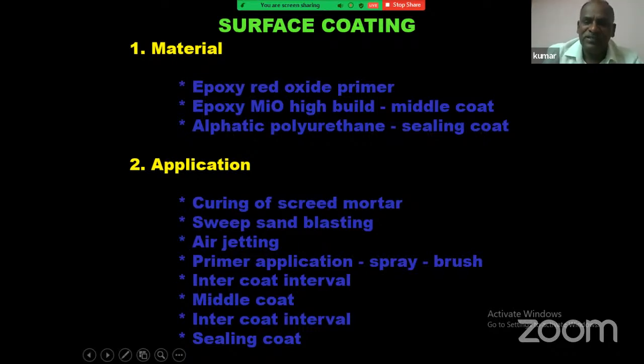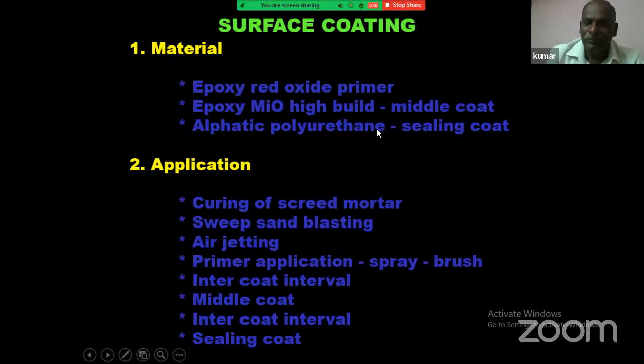That is why nowadays Asian Paints or anybody are using ultra coatings, which are polyurethane based. When the polyurethane is given on the outside of the structure, your coating system will be good. It serves the purpose. Otherwise, within a short duration, it will undergo degradation due to ultraviolet. So these are the material selections. Why is epoxy red oxide primer given? Because epoxy has very high adhesion with concrete. That is why epoxy is given.